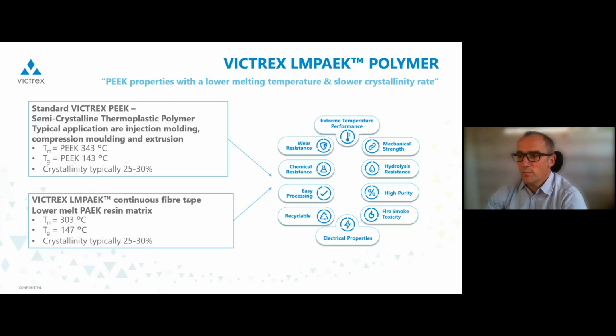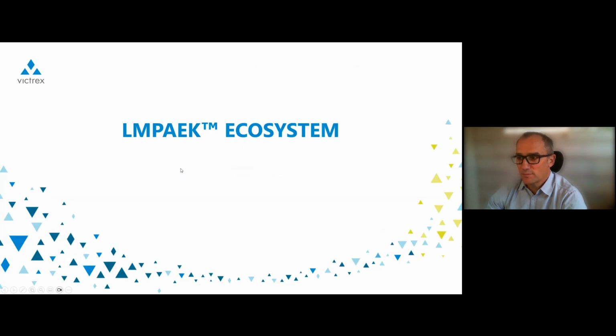Today we'll talk about PAEK polymer. Maybe you're already familiar, but just in case, we used to say that it has PEEK properties, so it answers the same problems, but with a lower melting point temperature and slower crystallinity rate. Typically PEEK's melting point is about 343 degrees. LMPAEK, which stands for low melt PAEK, has a melting point 40 degrees lower, around 303 degrees Celsius. This may sound like a detail, but it's massive, and it opens up a lot of manufacturing and processing windows. And that's where we make the difference.